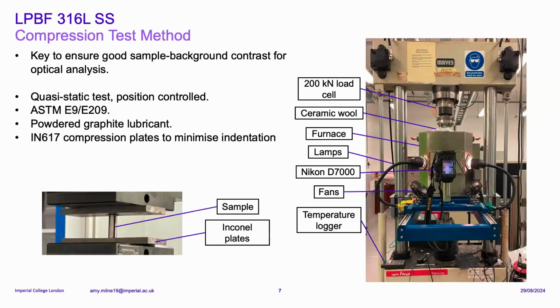So for the compression tests, you can see my setup here. I first placed the sample between two Inconel plates on the side, and then between the compression plates. I used a 200 kilonewton load cell to preload it to 2 kilonewtons, and then heated it up to temperatures between 20 degrees, which was room temperature, and 700 degrees, which was the highest test.